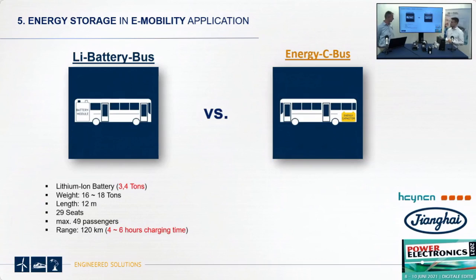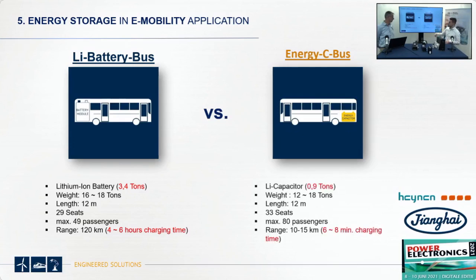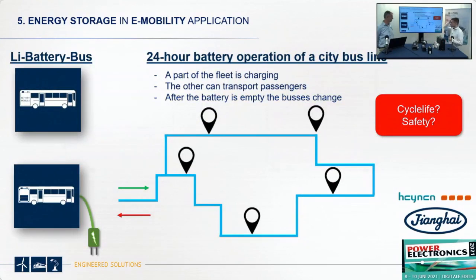In the past they used lithium-ion battery buses with a big pack of 3.4 tons and a range of around 120 kilometers, but with a charging time of 4 to 6 hours. And they changed this battery module to a capacitor module, which is much lighter and smaller. You reduce the volume of the pack, but the disadvantage is the range. But the benefit of this reduced range is the charging time. The charging time is much more reduced. We have time at each station to charge the capacitor. It's clearer when I go to the next slides.